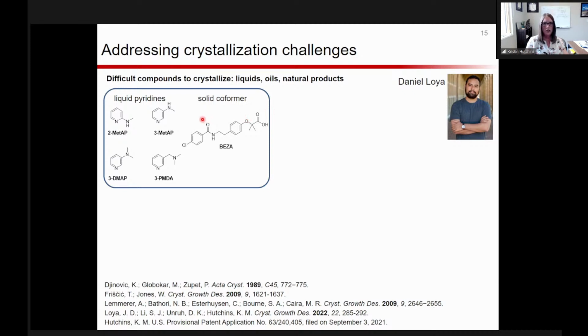And so we had been looking at this compound bezafibrate, which is an anti-cholesterol drug, and we had actually made the first ever co-crystals of that drug. And we went on to try to use some different hydrogen bond acceptors. So we've got this nice carboxylic acid on the bezafibrate, and we were trying to choose some pyridine compounds which could act as acceptors.